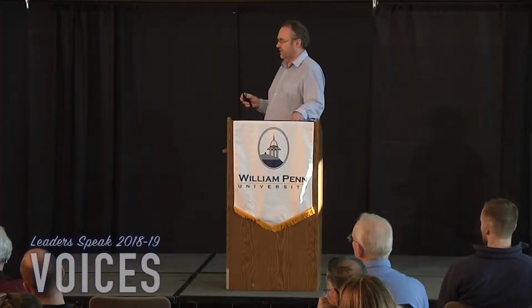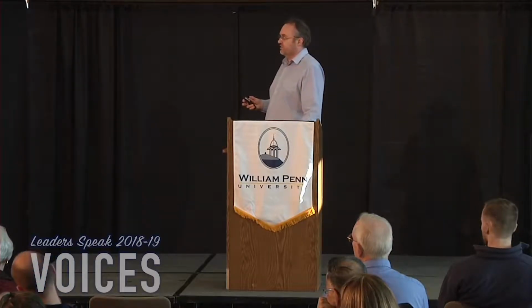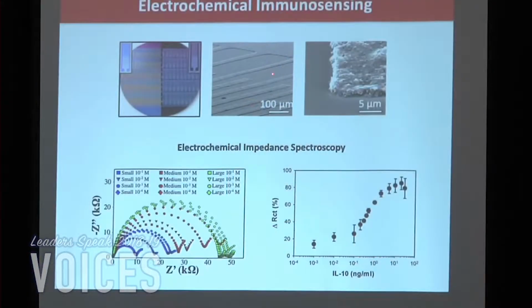But for immunosensing, that's when we immobilize an antibody onto the surface of these electrodes to detect antigens of interest that might be in solutions. We want a different type of circuit because we want to do impedance spectroscopy. So that's where we have those fingers where we need the high resolution. And that technique where we did the spin-coated graphene in the lift-off method allowed us to make electrodes that were suitable for antibody sensing.